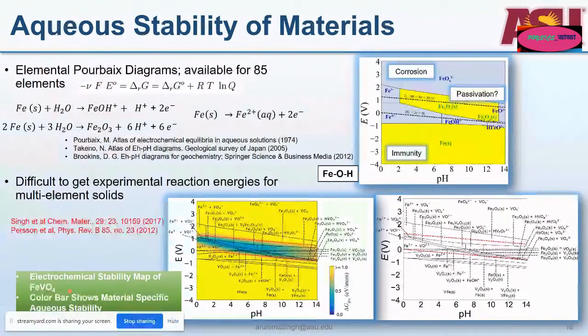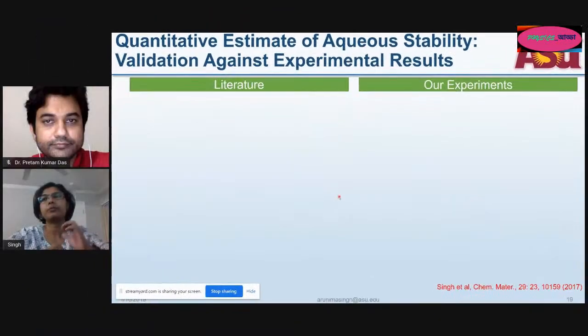What this color bar shows is that in this bluish region, FeVO4 is expected to be moderately unstable with respect to Pourbaix stable phases, but in these yellow regions, FeVO4 is very, very unstable, and it is expected to dissociate to the Pourbaix stable phases. We have this measure of the Gibbs free energy with respect to Pourbaix stable phases, and we thought that perhaps it could give a quantitative estimate for how unstable or stable a material is at a particular pH and a particular potential. So we did validations against the information we had in the literature and experiments which were done by our collaborators at Cal.